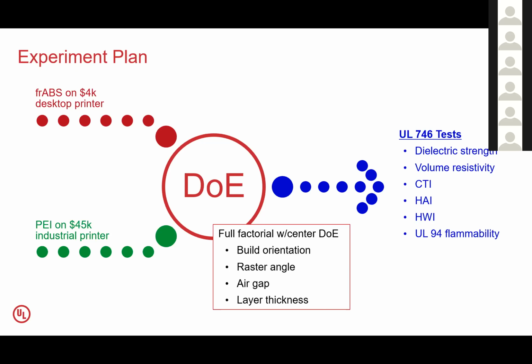We wanted to focus in on the key factors that a user can adjust. So not looking at all the different factors that impact 3D printing, but just looking at build orientation, the direction that we're printing it, the raster angle, the angle that we're depositing the adjacently layered materials, the air gap, how close those adjacent deposits are being put down, and the layer thickness, or in this case, we're using the tip size of our material extrusion 3D printer to guide that.